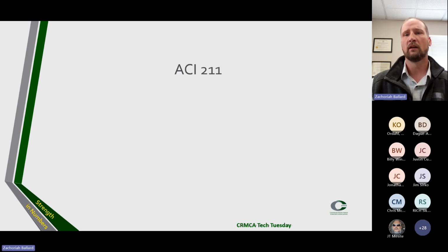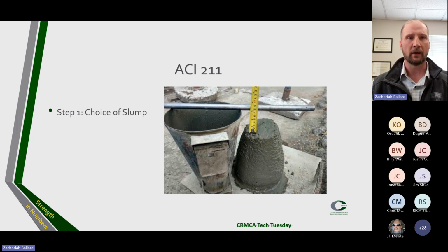So ACI 211, we're going to go over a real quick, basic introduction of how that mix design process goes. And the first step is our choice of slump. If slump's not specified, a value appropriate for the work can be selected from table 5.3.1 in the document. Those values apply to concrete produced without a water-reducing admixture. And these slumps range anywhere from 1 inch to 5 inches.